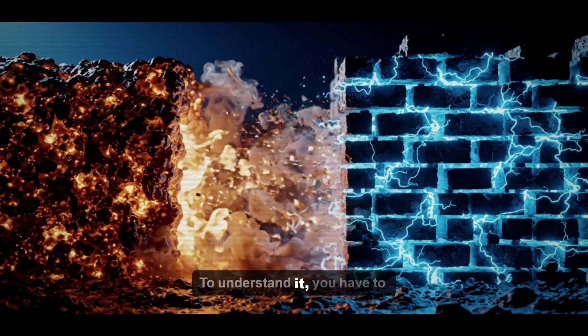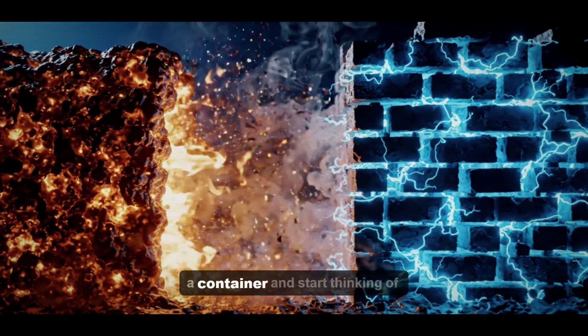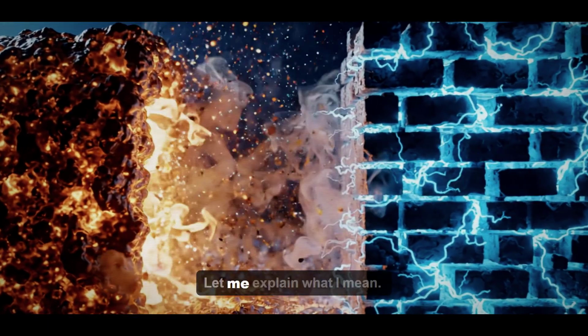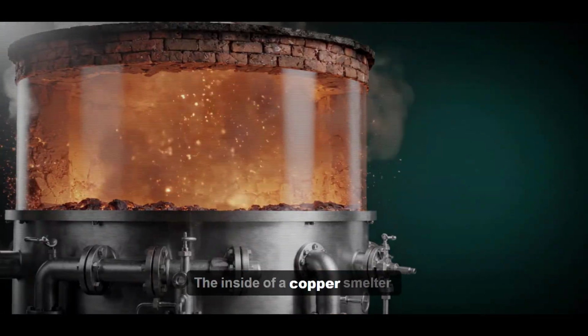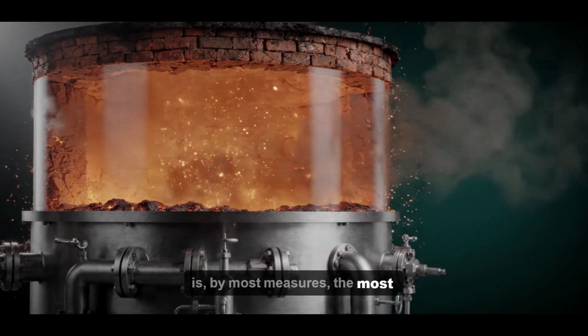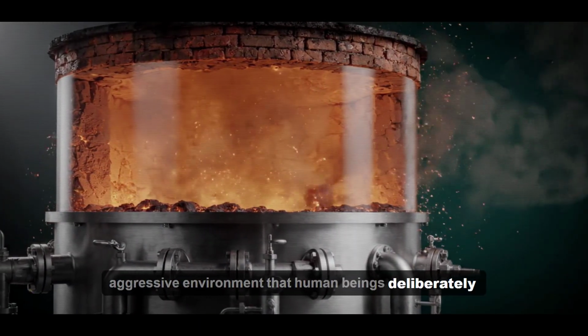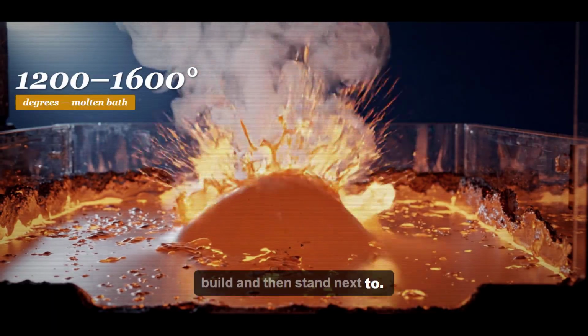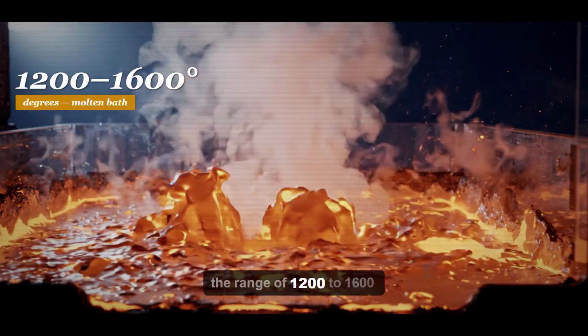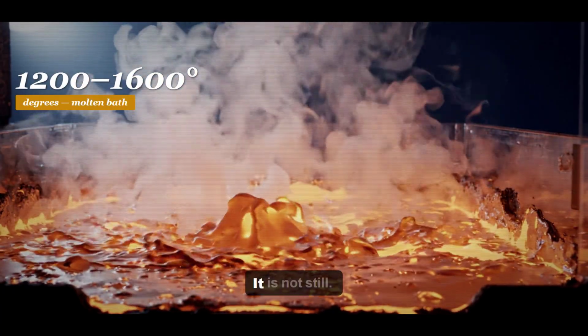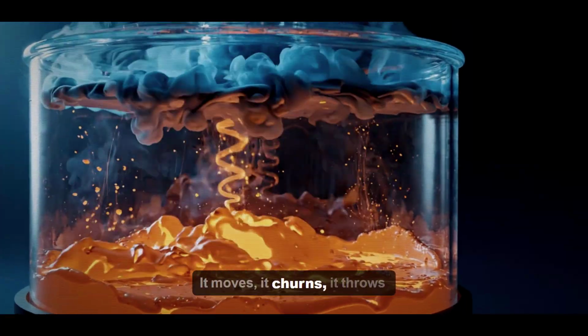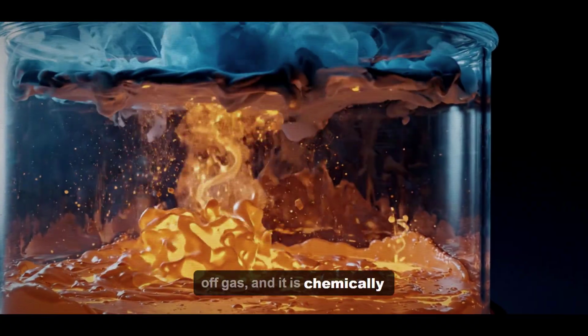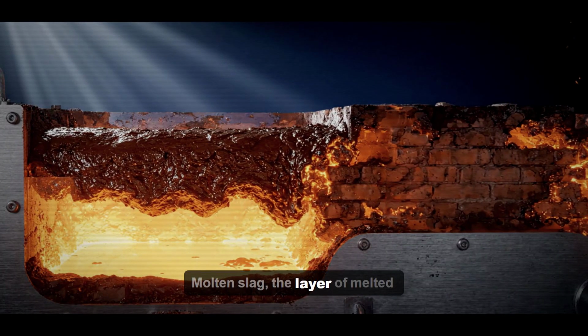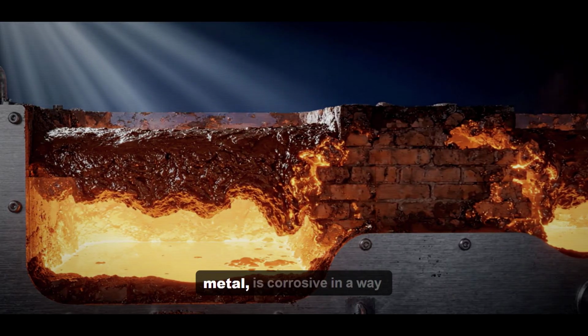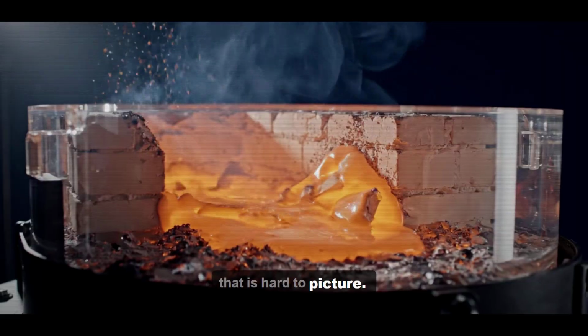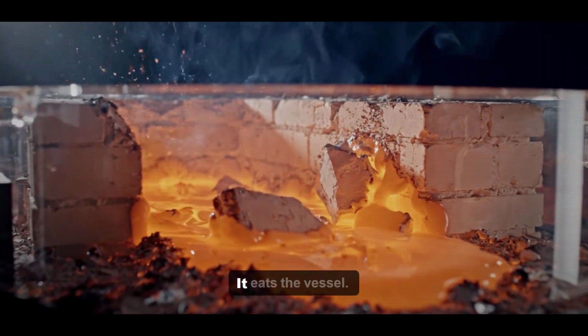To understand it, you have to stop thinking of a smelter as a container and start thinking of it as a truce. Let me explain what I mean. The inside of a copper smelter is, by most measures, the most aggressive environment that human beings deliberately build and then stand next to. The molten bath sits somewhere in the range of 1200 to 1600 degrees. It is not still. It moves, it churns, it throws off gas, and it is chemically hungry. Molten slag, the layer of melted rock floating on top of the metal, is corrosive in a way that is hard to picture. It does not just sit in the vessel, it eats the vessel.